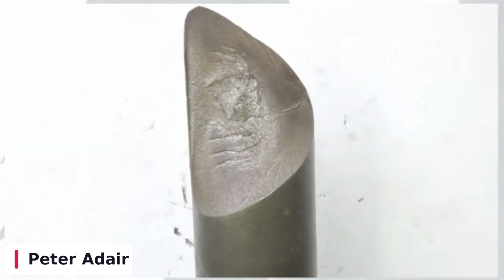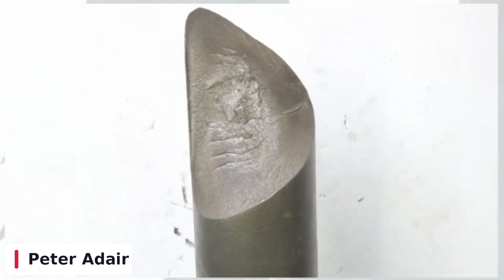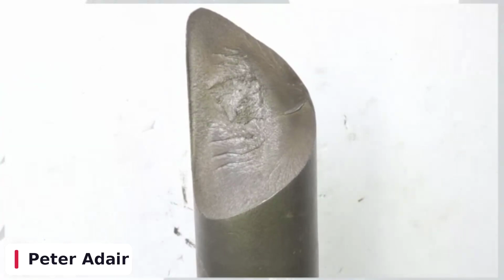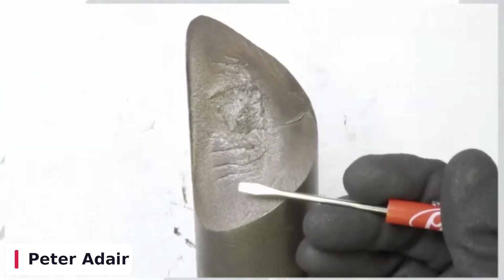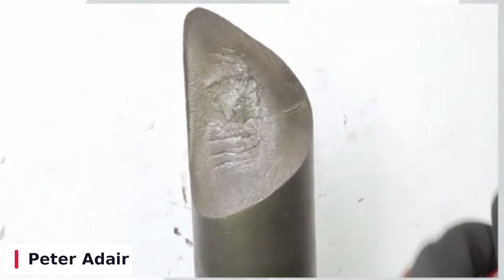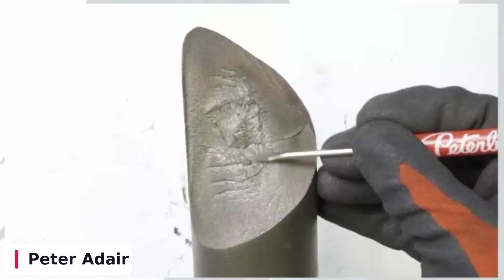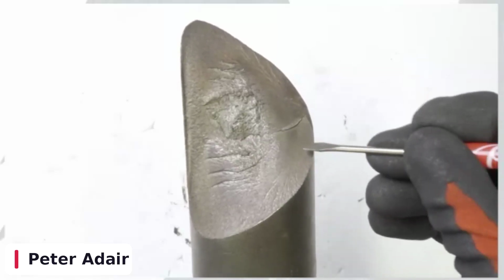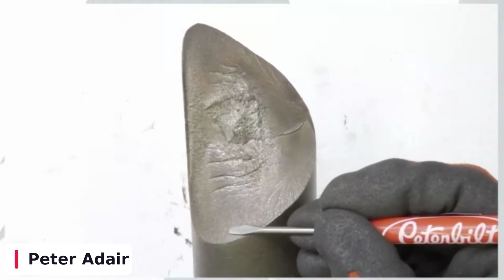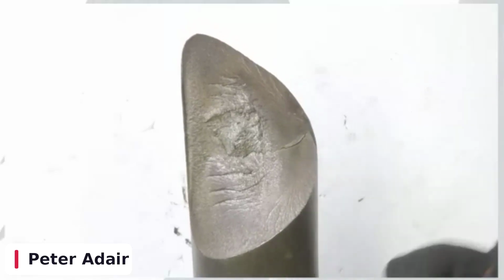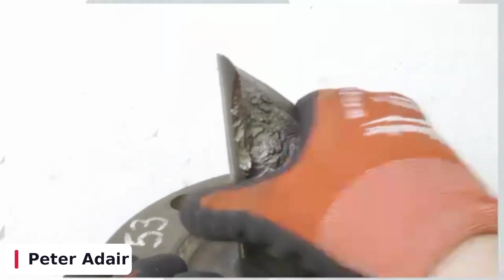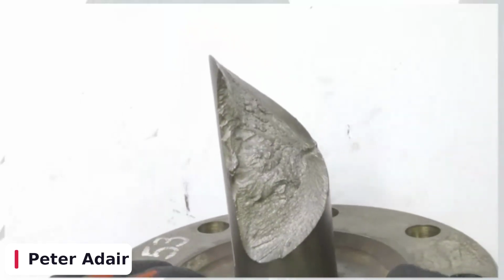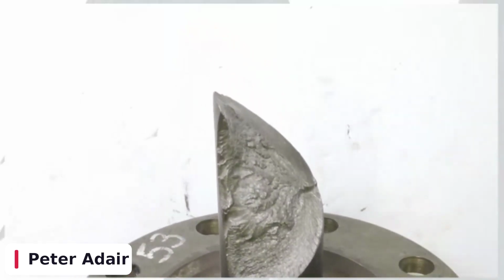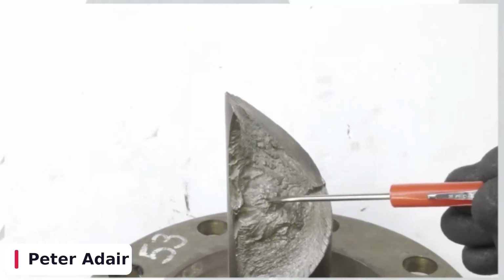It was just broken. So I could blame heat treat, and I could go, well, the heat treat was the problem. Well, if I look at this part here, I can see that it was heat treated. So I have a very coarse grain structure in the middle with a very fine grain structure on the outer edge. This fine grain structure, I'll show you my other example, which really shows that grain structure. Now you can really see that rough versus fine. So you can see the fine and then the rough grain structure.